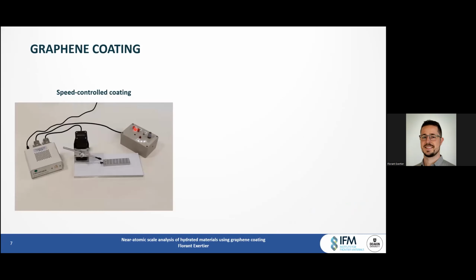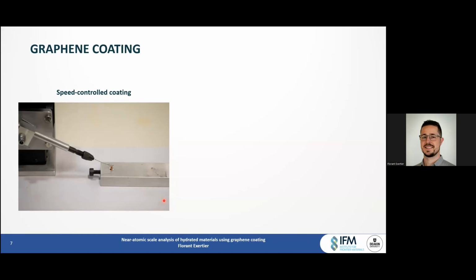In our case, we used a special device to control the coating speed, which is right here, and with a control box, which enabled us to tweak the speed. And in our case, the lowest speed that was used was 0.02 millimeters per second. And this is what it looks like up close.